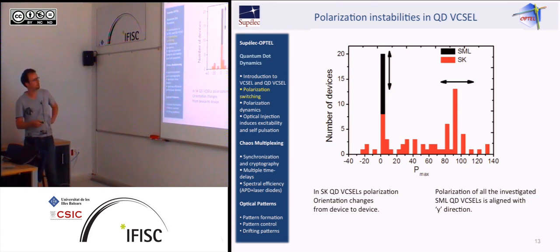So basically the initial polarization of all those lasers is almost randomly distributed. It has some maximum still around 0 and 90 degrees, which is the X and the Y polarization, like in quantum well VCSELs, but we have also other things that might happen. And in the submonolayer lasers, they are only aligned along the vertical or the horizontal axis, much less distributed. So those devices apparently do not have a naive polarization property. I mean, they initially lase with a polarization which is not necessarily linearly polarized along 0 or 90 degrees.